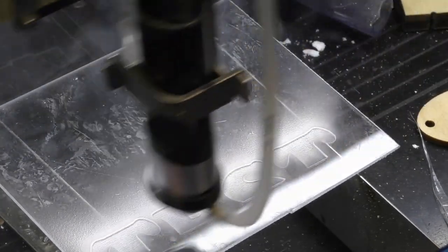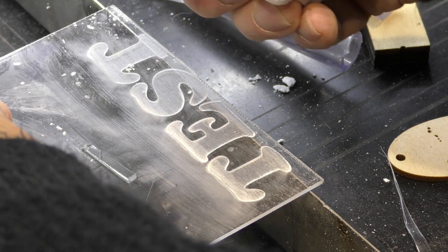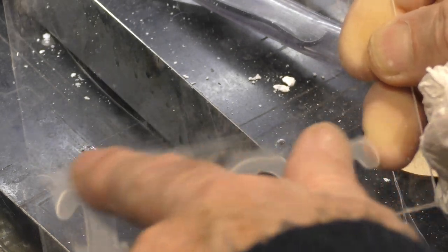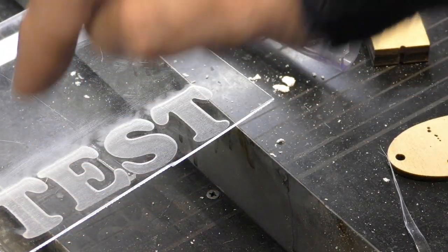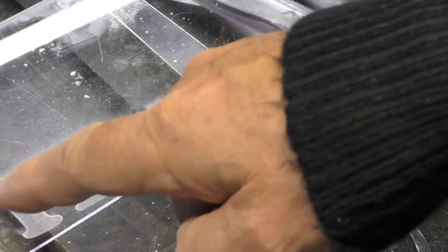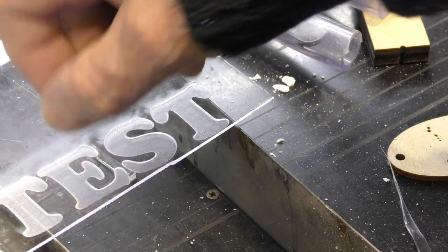Now, I've got quite a big air gap there and I've got quite a big nozzle on there. So I haven't got a huge amount of air assist blowing the fumes back down onto my job. The main reason for the air assist is to protect the lens. Now this debris here, look, it's just dust. Now to a certain extent we will be able to wipe this off. Look at the amount of actual solid, recondensed acrylic that we've got. And then look at all that haze that we've got on there that doesn't come off. Look around the T. I've smeared it and we certainly don't have white letters. There's another myth blown. So this comes back to understanding the material, how it reacts and how your laser machine is operating. There are ways of producing engraved text on acrylic without all this deposition. So you don't have to mask your job or you don't have to put hard soap on it or anything else to try and stop this deposition. Don't create it in the first place.